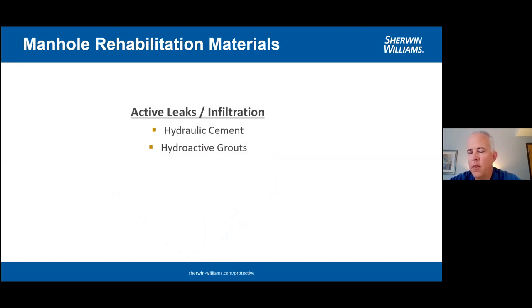I mentioned earlier the manhole that I went into that had about a 1-inch wide stream of water splashing off the opposite wall. We were able to stop that leak using hydroactive grouts. These are injection resins. I want to make mention of this technology, but we're not going to go too deep into it today. If you want more information on this type of technology, you can reach out to me or David. I'll give you our contact information at the very end of this presentation. But these hydroactive grouts work really well, are really simplistic to use, and really low cost as far as stopping groundwater intrusion from getting into our structures.